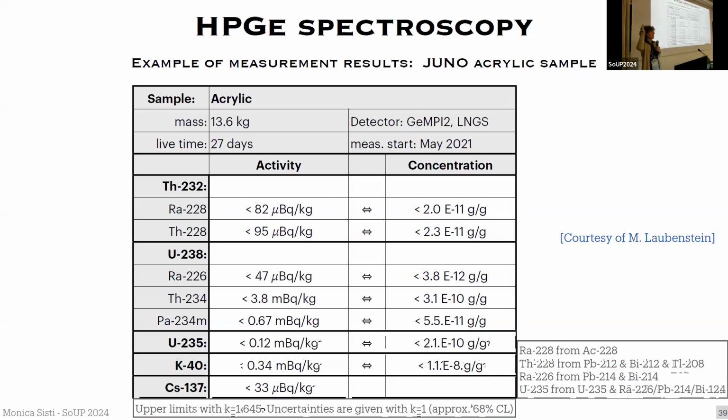So what you usually do, you have all the contaminations. Look at this, for example, here are all upper limits because this was clean, but in case you have a dirty part, you give the contamination of that nuclide, and then for the others at lower energy, you will give upper limits, because the sensitivity will be worse due to the Compton background given by the material itself. Okay.